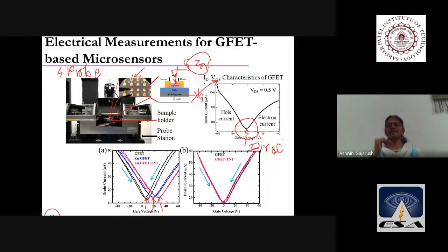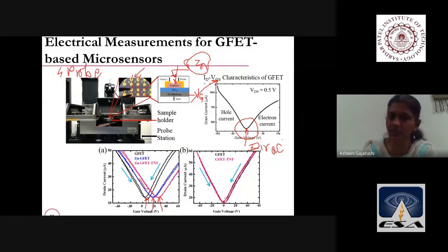For the cantilever system, we have seen delta R by R, or delta R, as a sensing parameter. For this particular system, change in the Dirac point is a sensing parameter. Now, if I don't modify the graphene transistor with the zinc modified chemical, at that time I won't see any shift when it is exposed to TNT. TNT is an explosive, trinitrotoluene. When it is exposed to trinitrotoluene material, it won't shift. So thus, this particular zinc metalated ion is helping the graphene transistor to become the sensor for TNT.